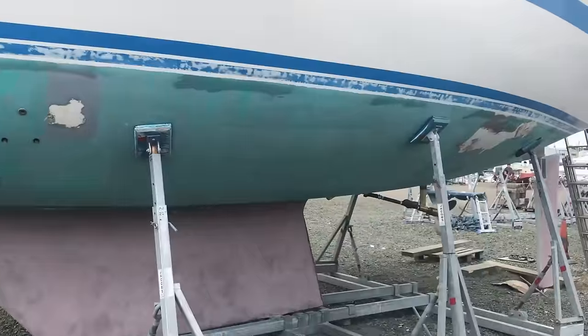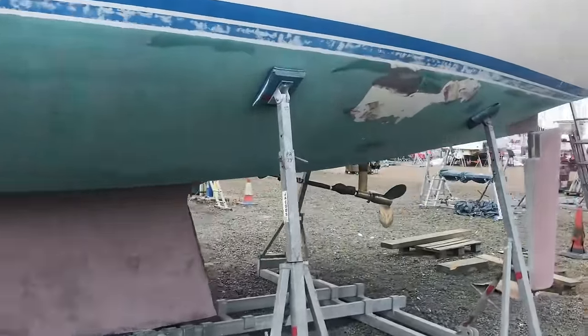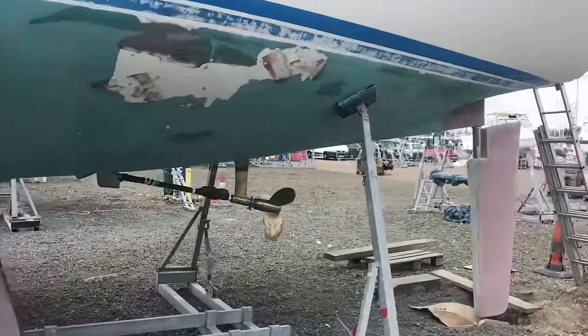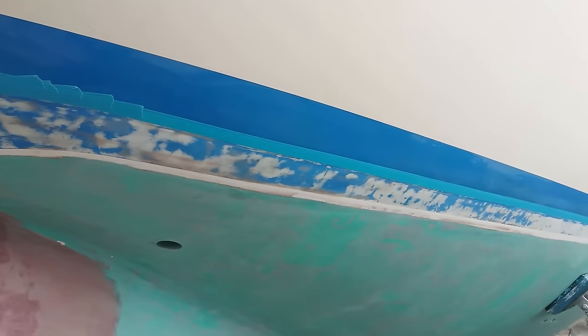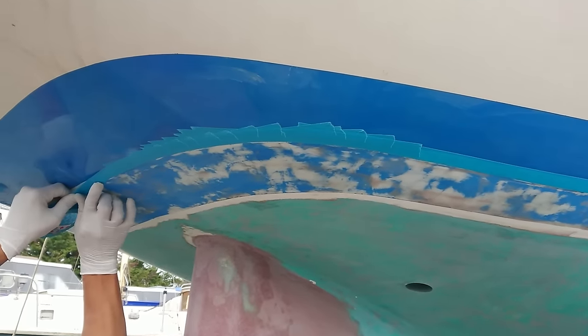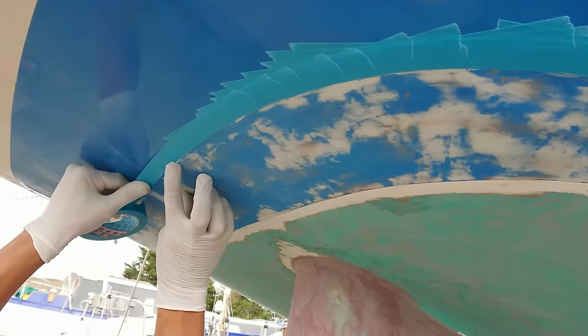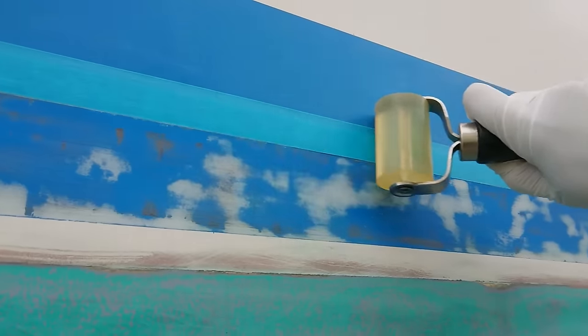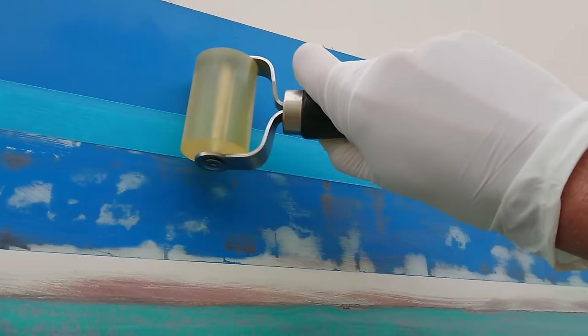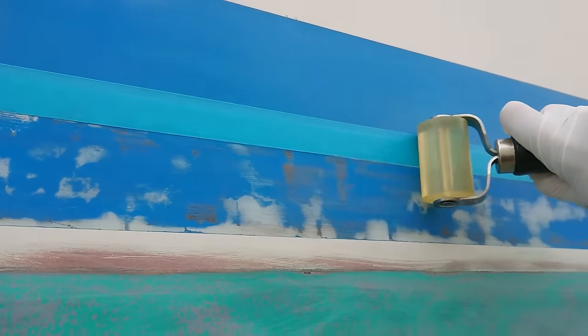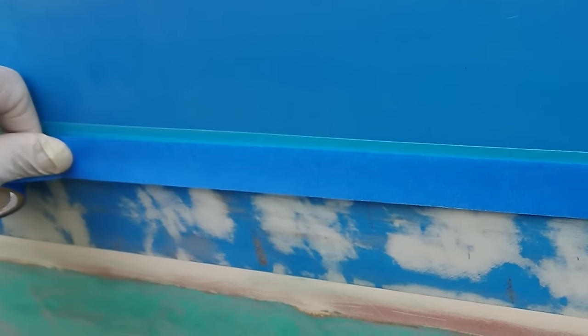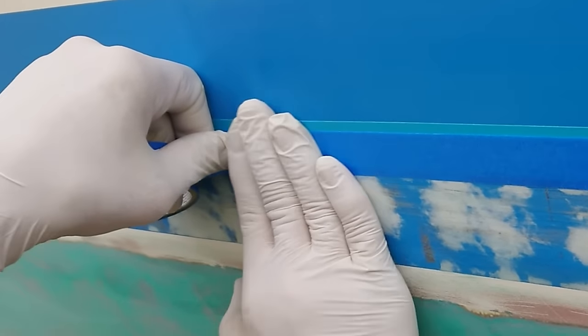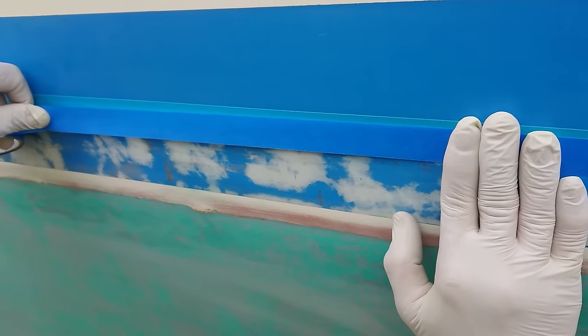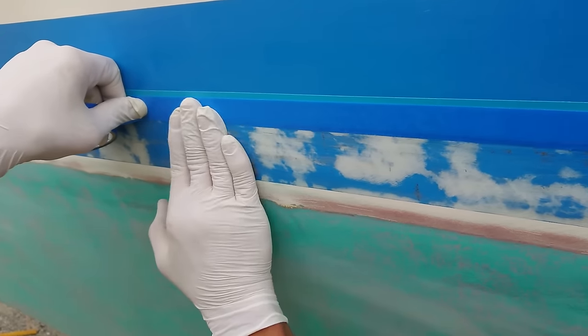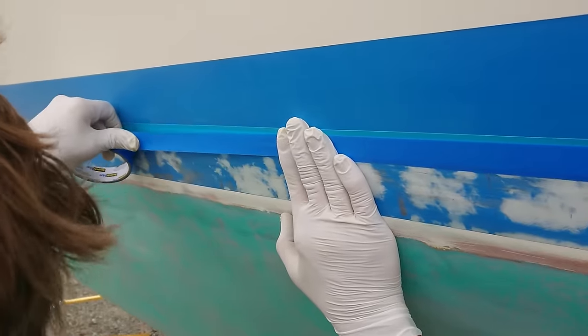There were four coats in total previously, but as we've prepped the hull, we've sanded some of this back, and so we're going to put another two coats of epoxy barrier coat over this, and two coats on the keel. And all of the other bare or unpainted areas under the waterline, we're going to be painting with four coats in total. The paint that's already on is International Gel Shield, and that's the product that we'll be using too. I'm overlapping two layers of masking tape here so I can stagger the edge a little. Even though the paint's quite thin, by the time we've added layers of copper coat over the top two, I don't want a lip of paint that's going to get damaged easily.